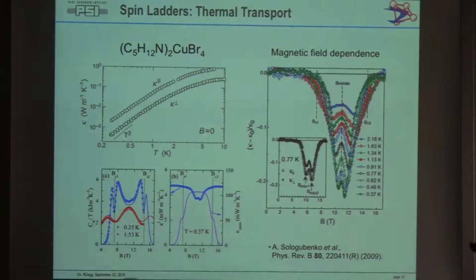Right now, I think our model was that we have relatively high quality samples, something like 0.5% of impurities. But for very 1D systems, maybe that's already enough to kill everything, in the sense that after 100 lattice sites, you come to some site which is blocked. It's very 1D, so there's no way you can go with the spinon to the next chain and continue. So the idea was that you simply somehow get stuck. And then, the field dependence of this process, we still have to figure out.